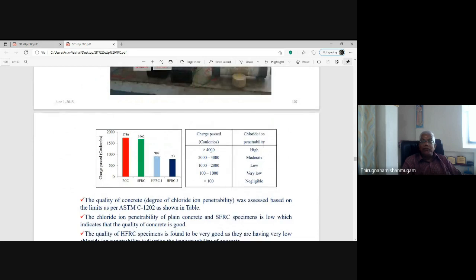If it is greater than 4000, high penetrability of chloride ion is possible, and if it is less than 100, negligible chloride ion penetrability is possible. But here, because of the good quality control, all the concrete specimens are exhibiting only low penetrability, 1000 to 2000, and HFRC are exhibiting very low chloride penetrability.